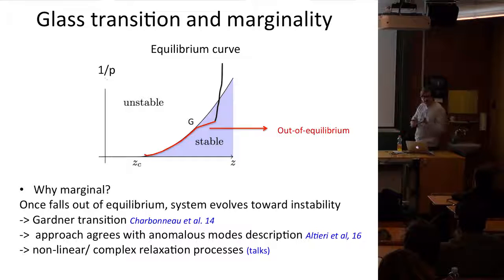When you become unstable, then you can think of being stuck in one metastable state. But then you compress further, and you adiabatically follow this state. What the results support, at least in infinite dimension, is that once you do that, in this phase diagram, when you compress further, you're again driven towards this elastic instability. So now you live in a well-defined metastable state, and you go toward an elastic instability, and then again you will have this buckling dynamics I described in the previous slides, which in their formalism leads to this Gardner transition and a fractal description of the energy landscape. And again, from their approach, that would lead to interesting nonlinear properties and complex relaxation functions.